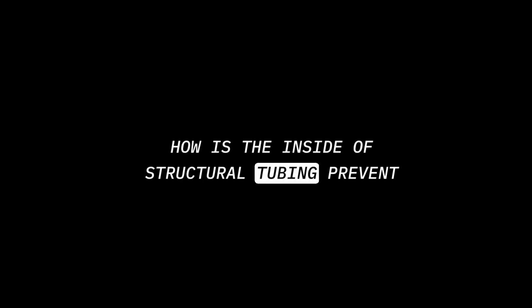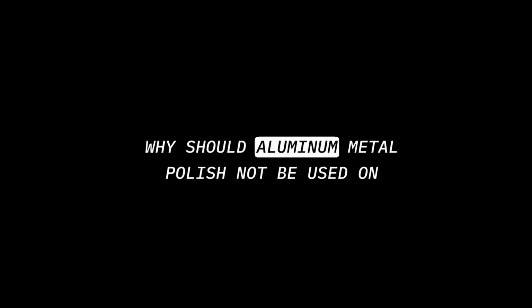How is the inside of structural tubing prevented from corroding? Hot linseed oil can be poured into the hole, then the excess is drained. Why should aluminum metal polish not be used on anodized aluminum surfaces? It will remove the oxide coat. Why is the aircraft cleaned before inspection? It enables the mechanic to conduct a more accurate inspection. What geographical location promotes corrosion? Coastal regions.